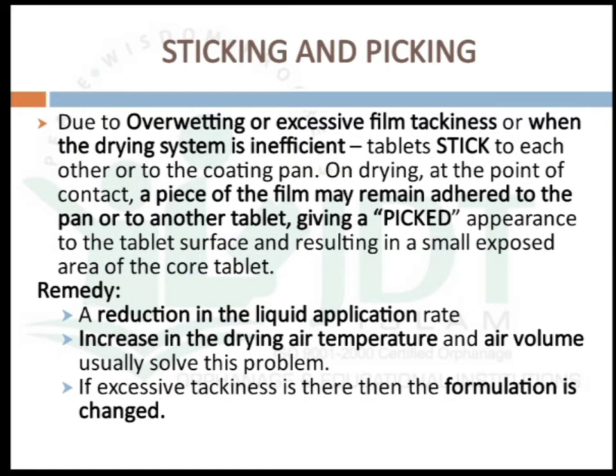The first defect is sticking and picking. This occurs due to over-wetting, excessive film tackiness, or when the drying system is inefficient. The tablets stick to each other or to the coating pan. At the point of contact, a piece of film may remain adhered to the pan or another tablet, giving a picked appearance to the tablet surface and resulting in a small exposed area of the core tablet. This can be rectified by reducing the liquid application rate or by increasing the drying air temperature and air volume. If excessive tackiness is present in the formulation, the formula must be changed.